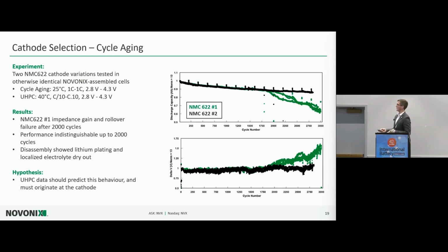And so these experiments here are showing two different cathode materials. These are both NMC 622s. And we cycle these for a few thousand cycles, and it takes 8 or 9 months or so to get to 2,000 cycles. And there's no sign of any difference between these materials in this long-term 1C cycling.